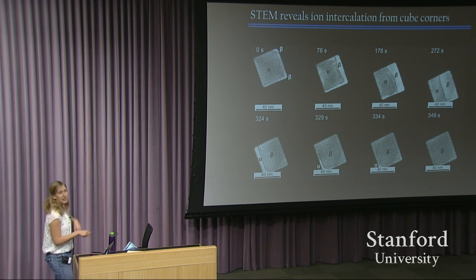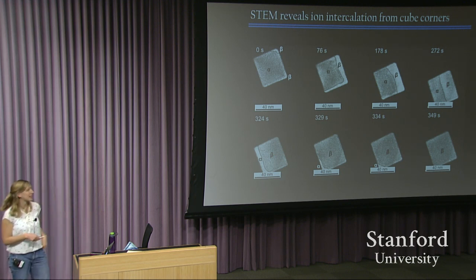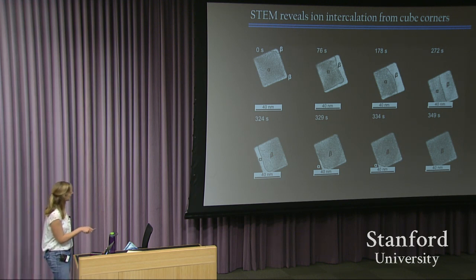Here we've got the beta phase. The contrast has kind of switched. I can explain that in the Q&A session if you're interested to understand why. And then the beta phase grows across the nanoparticle, eventually pushing the alpha phase out through a corner of the cube.